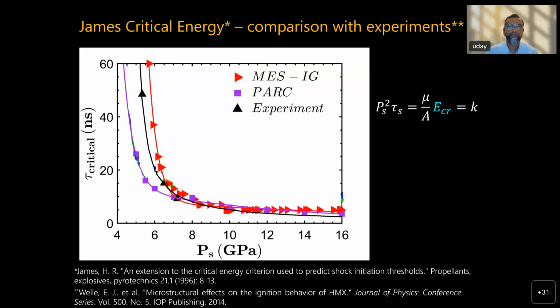So I think there is definitely some kind of a mechanism transition, because below about 5 GPa or so, you really don't get criticality. So the void may collapse, but it collapses so weakly that you don't get criticality. So there is something happening here, first of all, in terms of the mode of collapse and the strength of the material playing a role. But secondly, I think this region is much more sensitive to the chemical kinetics models, and we've done quite a bit of examination of that.